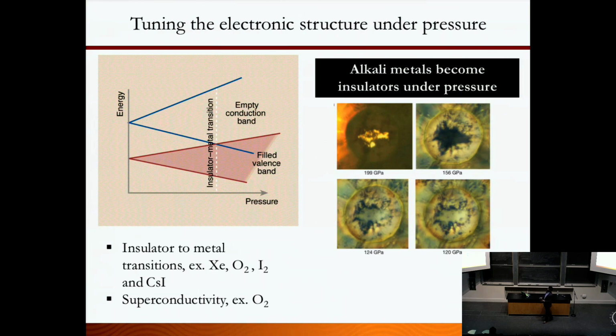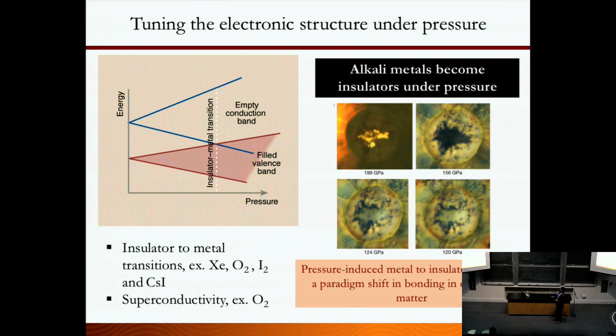But not everything. Some go in the opposite way. It's just so fascinating to understand why. So, for example, alkali metals, sodium or other materials in the alkali group, when you squeeze them, they go transparent. They go to an insulator. So does lithium. Lithium is a superconductor, but at higher pressures it goes to a semiconducting to insulator transition and goes back again to a metal. So this is a change in the paradigm of the bonding. The reason for this is that the electrons make a bond in interstitial sites in the sodium. So when you squeeze to really higher pressures, that gives you a new bonding and it becomes transparent.